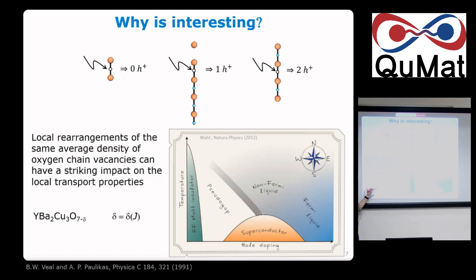So what people have done so far is build up this phase diagram by making a sample with this oxygen content, and this oxygen content, and this oxygen content, every time under different oxygen conditions, different samples. What I'm proposing is that we come to the chemical formula: this oxygen doping, or whatever delta you have over there, is now a function of current. So I have only one sample. I apply current and I change this, and I can build up the whole phase diagram just with current. And even better, I can put them back.